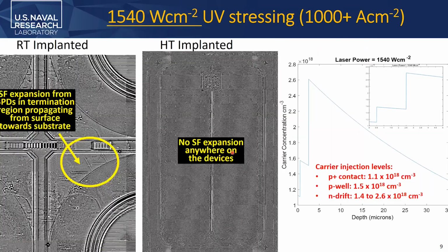But after we increase our carrier density, and here we are basically having a carrier density of around 1 times 10 to the power 18 in the P plus contact layer, we see that in the room temperature samples, from the termination region, we start to see these defects, and that will be a big reliability concern. So at normal typical operation, it does not fail. But when you do a high injection condition, then these room temperature implanted samples start to fail, but they only fail in the termination region.